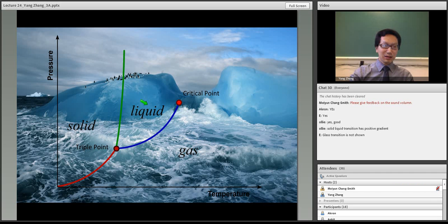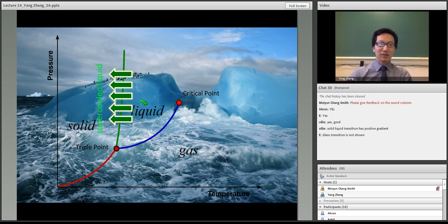Since we talked about the glass transition, we should mention this. The liquid-solid phase transition line, the first order phase transition line, can actually be bypassed from the liquid state. If we cool down a liquid carefully enough, or if the liquid is very pure, or there's no external perturbation, sometimes we can enter the solid region of the phase diagram without crystallization. This phenomenon is so-called supercooling.